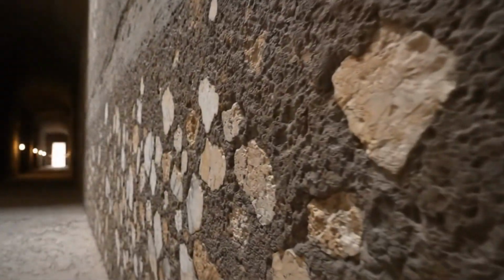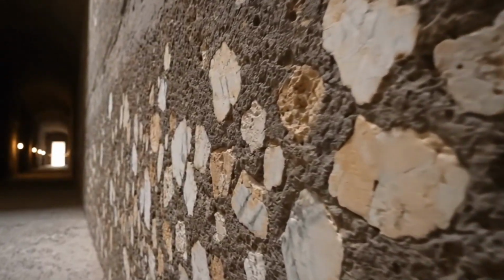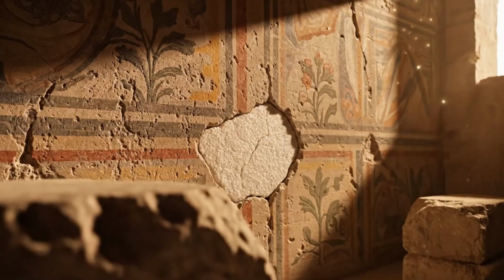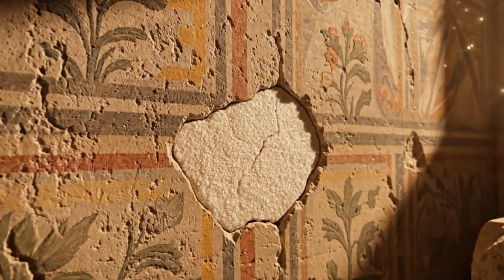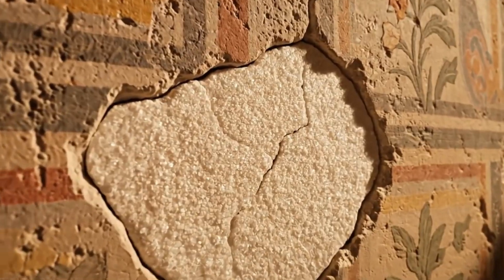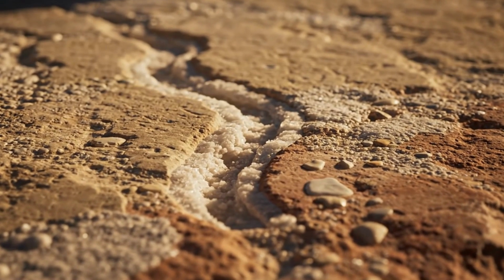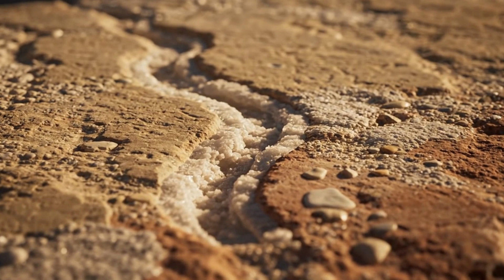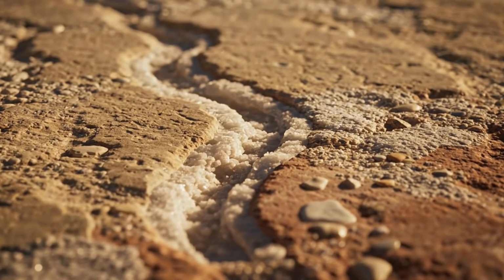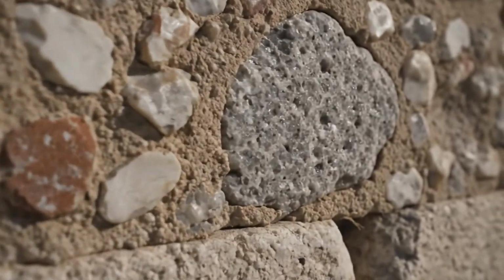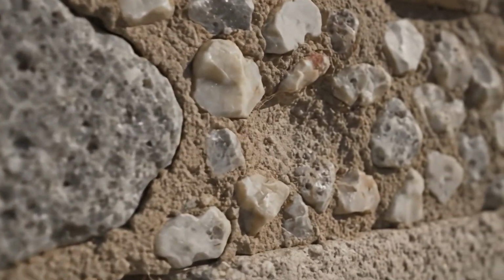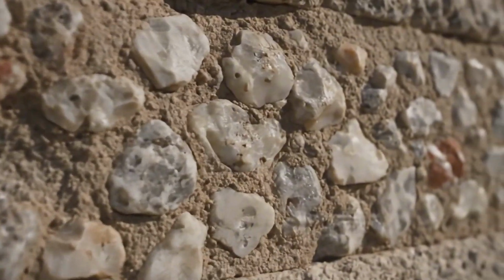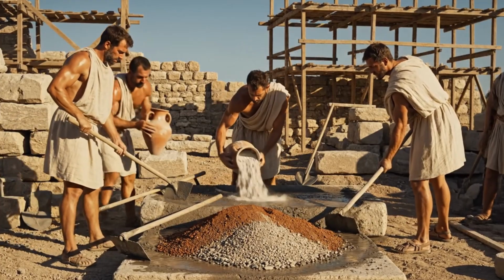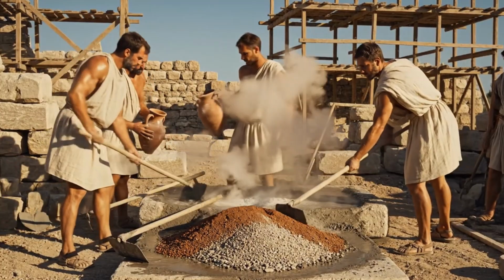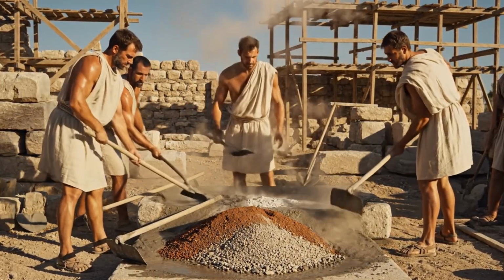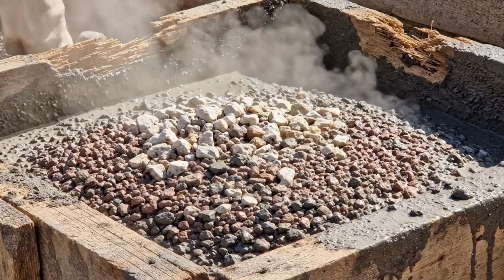When small cracks begin to form in the concrete over time, they tend to propagate through the high surface area lime clasts. As water enters these newly formed fissures, it interacts with the reactive calcium contained within the clasts. This reaction produces a calcium-rich solution that can migrate into the crack. As conditions stabilize, the dissolved calcium can recrystallize as calcium carbonate, effectively sealing the fracture. In some cases, it may also react further with surrounding pozzolanic materials, strengthening the composite structure even more.